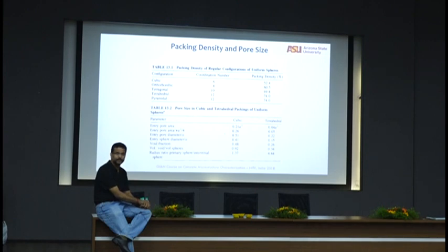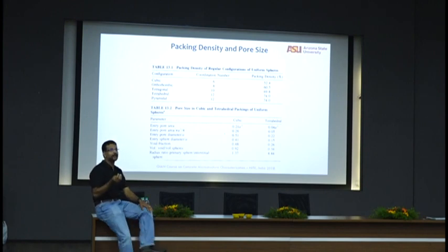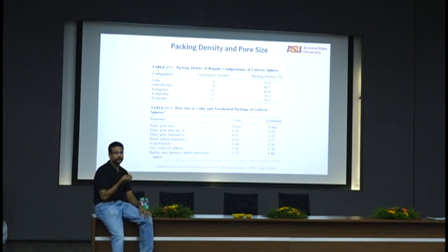Is it for strength? For durability, right? How my pore space is organized is the only thing that dictates how chlorides and sulfates and moisture and all of these things go inside concrete. Period. You can tell me that I have only 10% porosity, but if the 10% porosity is really well connected, that is very bad. You may have 20% porosity as one very big hole inside the concrete, but the outside is beautiful. Your durability will have no problem at all. So again, pure numbers will not tell you the whole story.